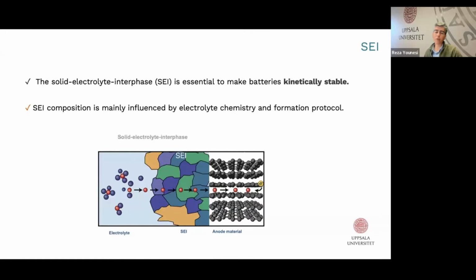This is very interesting — we are working with a system which is not thermodynamically stable, so we need to make it kinetically stable. You could think of it like pure aluminum exposed to air: an oxide layer forms on the surface, and that oxide layer makes the bulk aluminum stable, so there is no further corrosion. We expect something similar here — by this SEI, we make the system stable to ensure there is no decomposition.